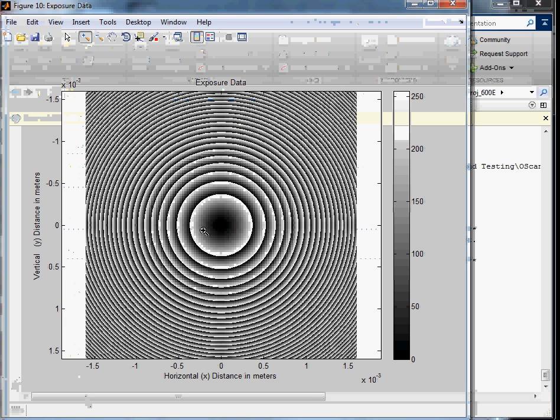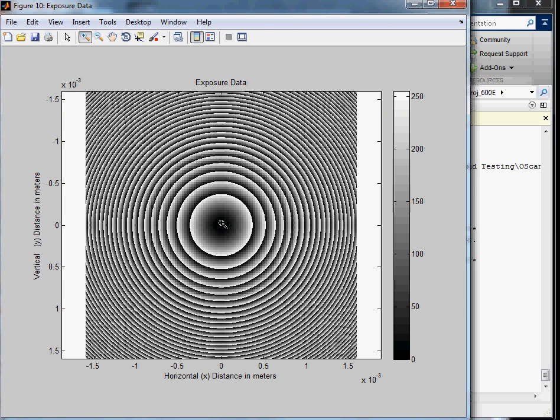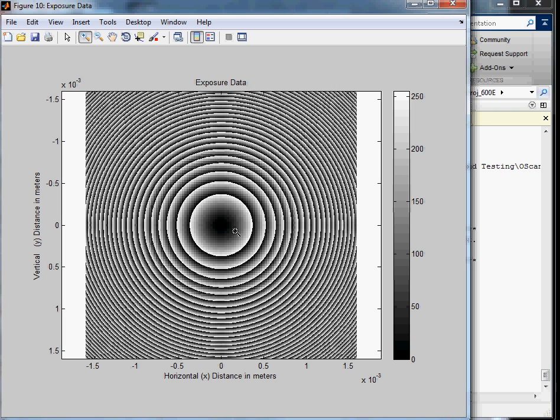All right, so what's happening here is the laser writer is going to be dark here in the center. Since it's a positive photoresist, as the laser power increases here, this is increasing quadratically, more and more material is going to be removed. So it's going to be a positive lens when it's actually written and developed, although it's kind of a negative lens shape here in the file. So this is not the phase. This is the writing file for the maskless lithography tool.